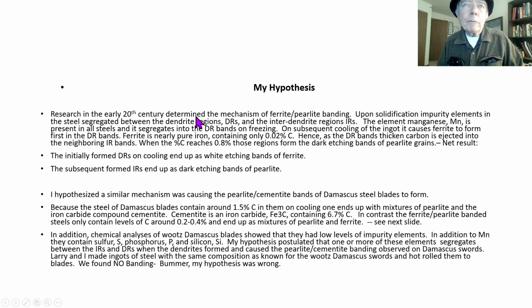Research in the early 20th century, probably around the 20s, determined the mechanisms for pearlite banding, and it turned out to be interesting and complicated and difficult to figure out, but they did it. And I used a similar method to do our research. Upon solidification, impurity elements in the steel segregate between the dendrite regions, the DRs and the IRs, the interdendritic regions. The element manganese is an example of an element that is segregated. It ends up in the DRs in freezing, and on subsequent cooling of the ingot, it causes the ferrite to form first in those DR bands.